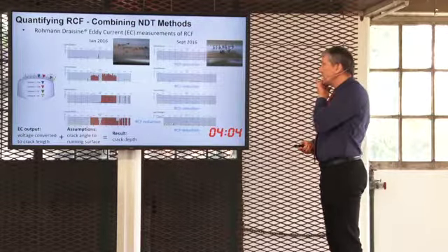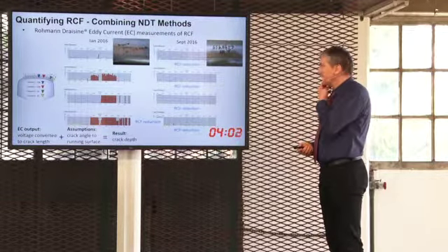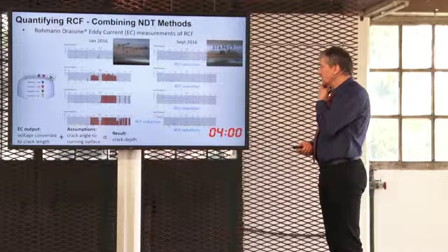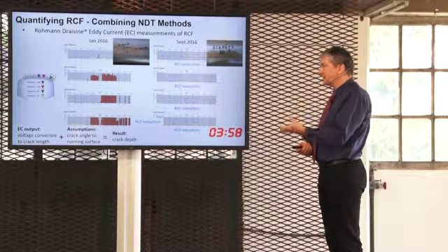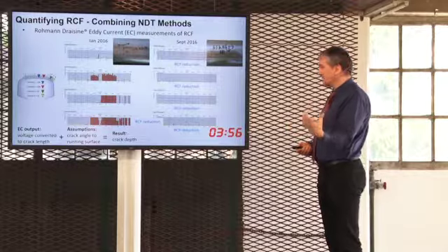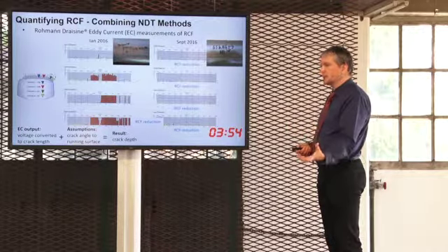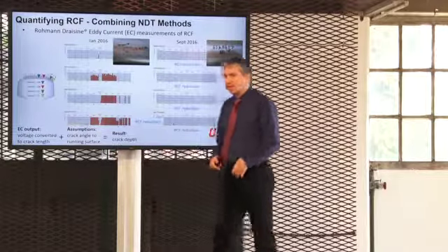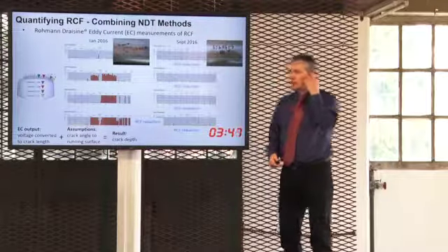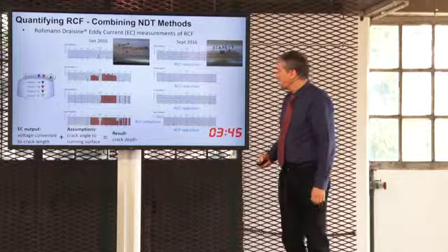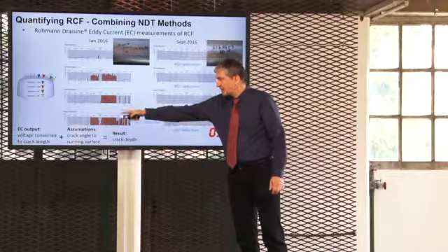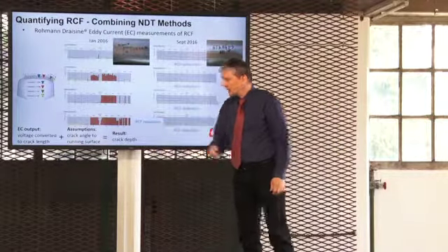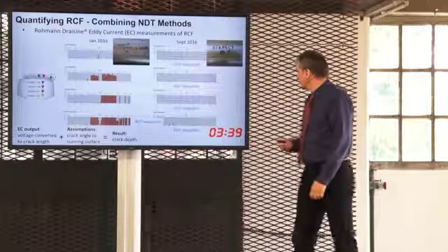Now, we want to combine this information with eddy current data. The eddy current right now measures the voltage drop, and that gives you the crack length. That's the measurement, the crack length. But the crack angle is an assumed value. It's not a measured value right now. And the result is a crack depth. So something that's measured, something that's assumed, and the result is a crack depth.